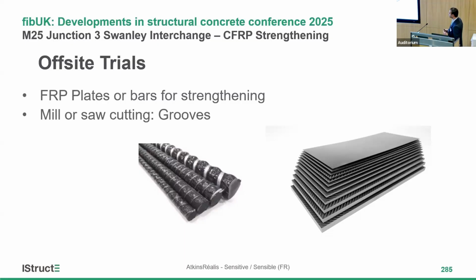The FRP plates are not that far off from the steel plates. The only advantage is that the thickness of this element is much less than the steel plates. Whereas, as Professor Sen presented in the previous session, the advantage of using the NSM is that it has a better bond with the concrete element, and it takes less time to apply on the structure. Whereas for the FRP plate, the surface preparation takes a long period of time. And the other trial was to see if we need to use mill cutting or saw cutting to execute the grooves for the NSM bars as well.